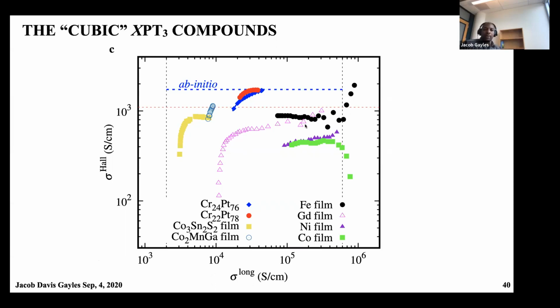Furthermore, what you can see is that you can distinguish these different materials from this graph. So on the right, you have these elemental metals, which show pretty much a flat and constant anomalous Hall effect, which is this intrinsic effect. And then once they start to get to high conductivities, they become skew scattering materials, and the skew scattering starts to dominate the anomalous Hall effect.